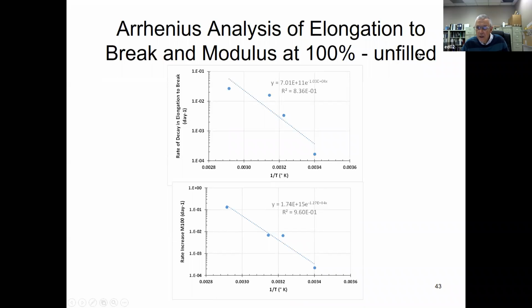And here's the unfilled: decay in elongation to break, plotted on an Arrhenius plot. Rate of increase in M100 plotted on an Arrhenius plot. In both cases, no evidence of a mechanism change around 40 or 50 degrees centigrade.